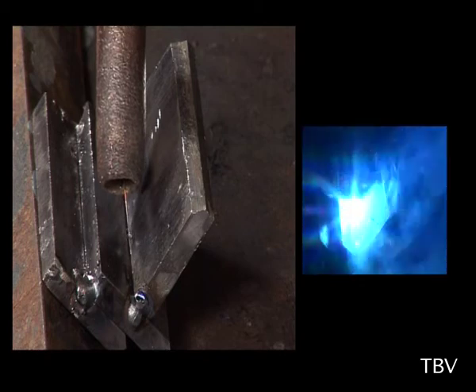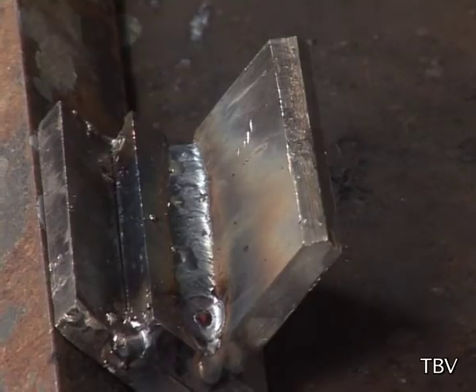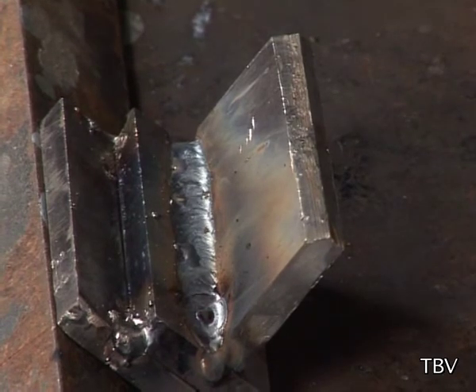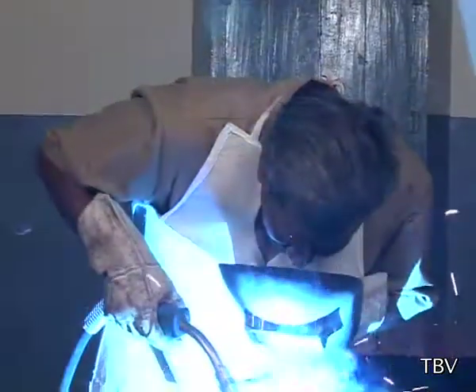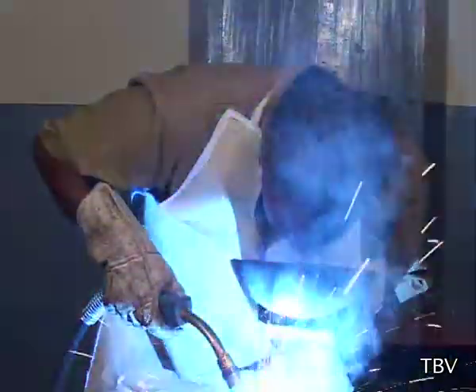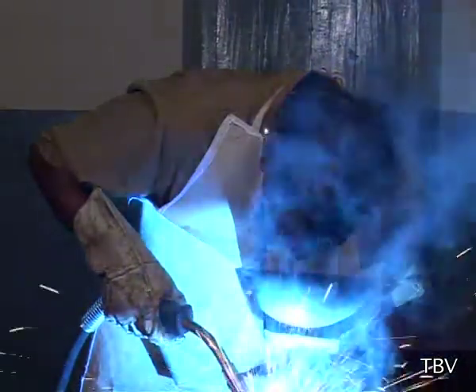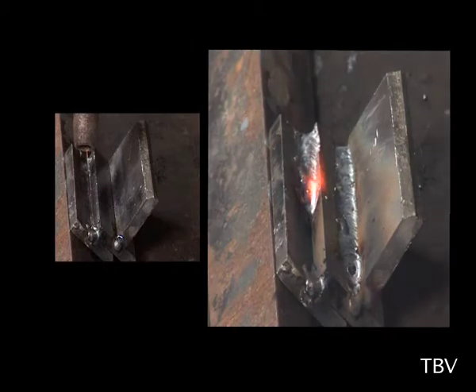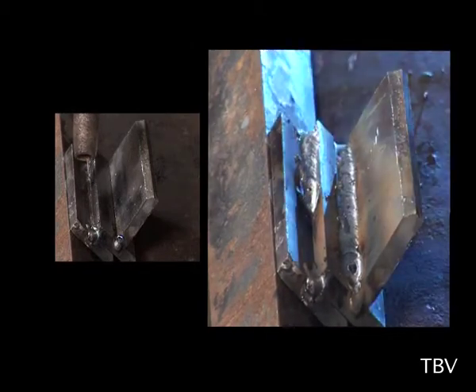Deposit the bead on the tack welded job piece from one end to the other. Weld to full length of the workpiece by filling the material in the weld area, moving forward or backward. Let it cool at atmospheric temperature for 5 to 10 minutes. Then, fill the next joint. Remember, the angle between the T-plate and the gun should always be 45 degrees. The angle between the electrode tip and the base of gun direction should always be maintained between 10 to 15 degrees.